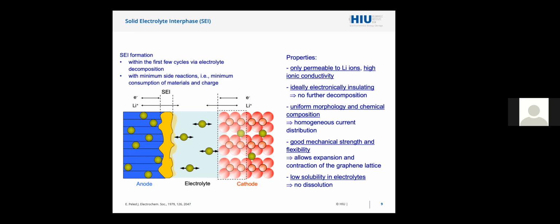So the first property, very important, is that it should be only permeable to lithium ion and have a very high ionic conductivity, because we obviously want lithium to go through the SEI into and outside of the graphite. It should ideally be electronically insulating, because if this doesn't happen, the electrolyte will keep decomposing forever, and we will see that actually this is a problem for silicon. We will see later. It should have a very uniform morphology and chemical composition in order to guarantee a homogeneous current distribution through the whole electrode.